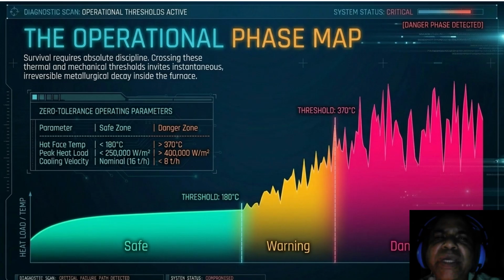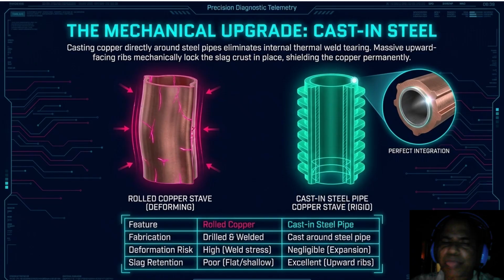So coming to the mechanical upgrade, here is the solution to the mechanical failures we have discussed: the cast in steel upgrade. On the left you see a standard rolled copper strip in pink. It is deforming under weld stress and has shallow ribs that cannot hold slag. Now look at the cyan, that is the cast in steel pipe copper strip on the right. By casting copper directly around steel pipes, we eliminate internal thermal weld tearing.